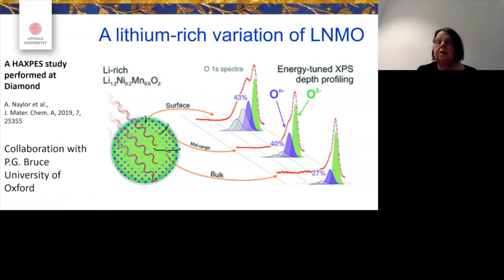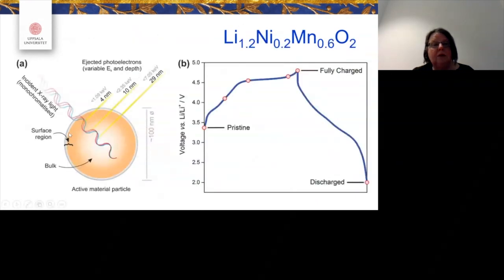I think we were one of the first to really show it, with Laurent Duda some years ago, but I think that's forgotten. And it turns out that we can say that we have in the spectra two different oxygens and an oxidized oxygen on the surface, that can show that the oxygen is really part of the redox process. And what you normally do when you do these experiments is, of course, very time consuming. You make an electrode, you put it at a certain place in the discharge cycle, you let it equilibrate, you open your cell, you wash it, and then you make your measurements. So you understand there are many samples you have to work on.